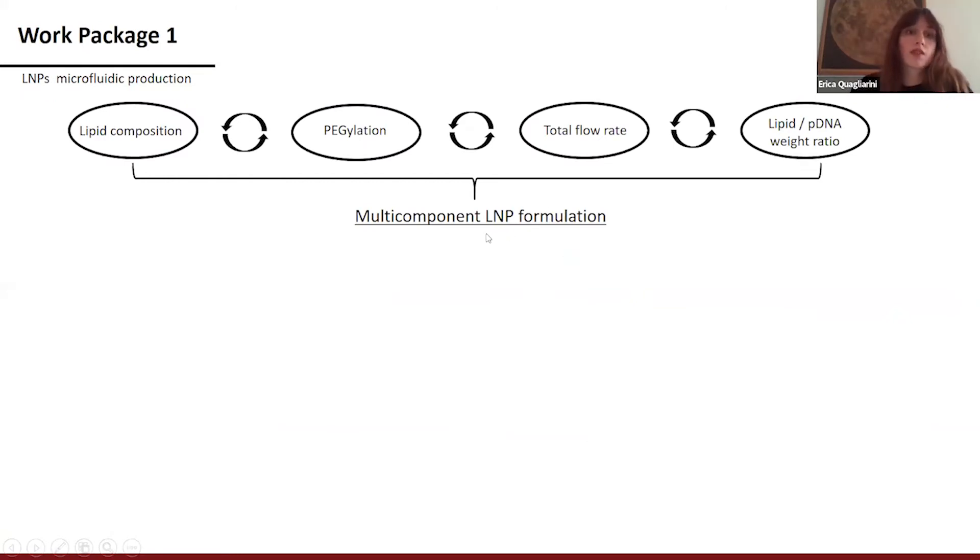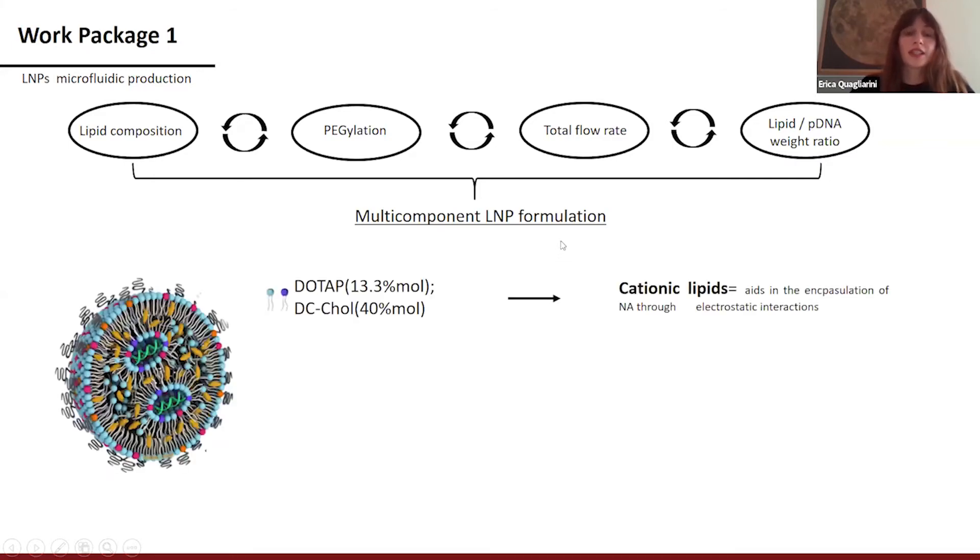So let's start. Our first theme was the investigation of several factors affecting the synthetic identity of the system by performing systematic changes in different factors such as the lipid composition, the microfluidic parameters such as the total flow rate and the lipid pDNA weight ratio. This allows us to generate a library of lipid nanoparticles, multi-component lipid nanoparticles that were small in size and highly homogeneous. In particular, the latest development about the lipid-based gene delivery system has highlighted the greater transfection efficiency of multi-component type lipid nanoparticles, with respect to the single and binary systems.